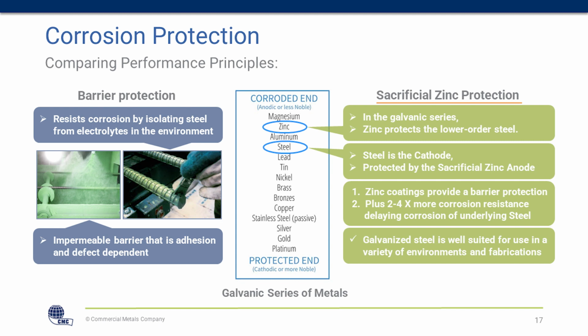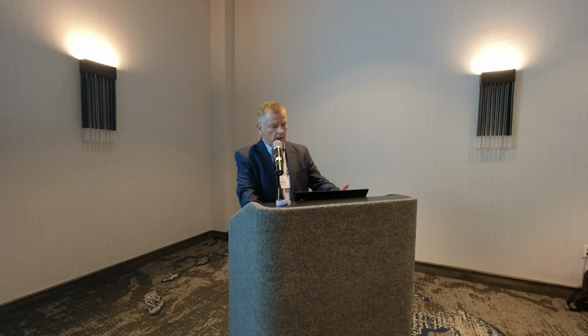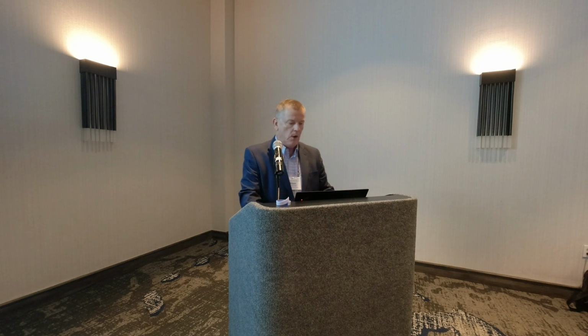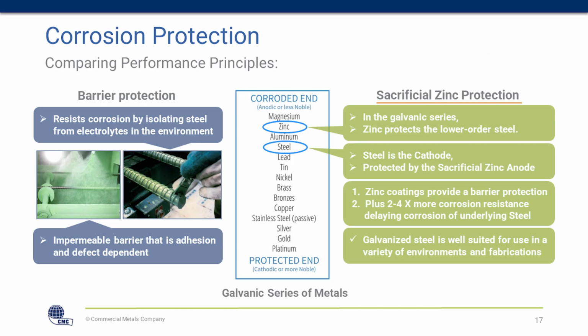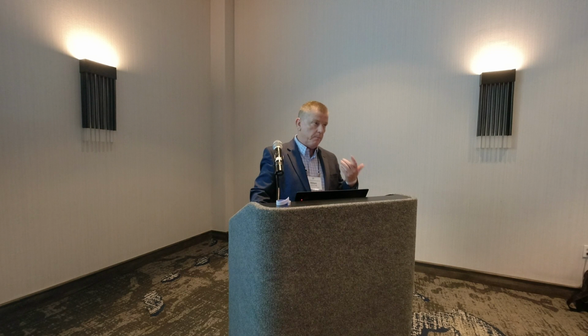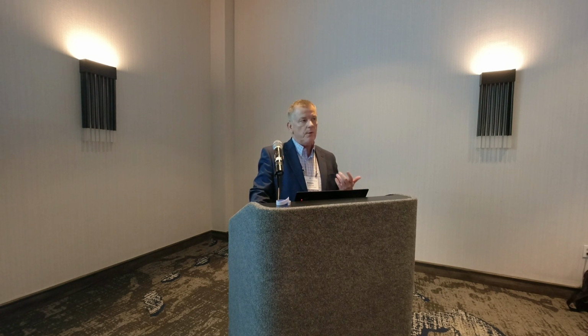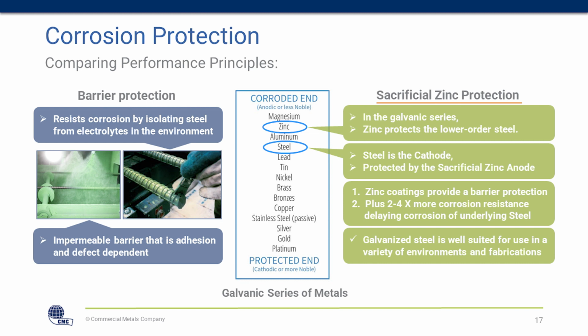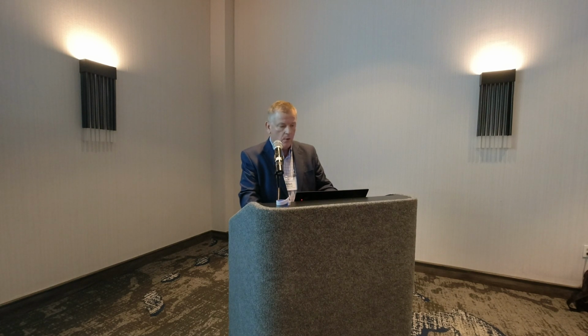There's actually a good workshop tomorrow in Section 8 that I'm looking forward to attending myself. It'll go through some of this system as far as the cathodes and the anodes. In this sense, any of the metals that are above will protect the metal below in the order. So zinc, you see, is well positioned to protect steel and to serve as a sacrificial anode. And in addition to a barrier protection, this is providing 2 to 4 times the corrosion resistance, delaying corrosion for the underlying steel, but then also not only is it in a good position on the galvanic series of metals, but it's well suited for a variety of harsh environments to also provide better corrosion resistance.